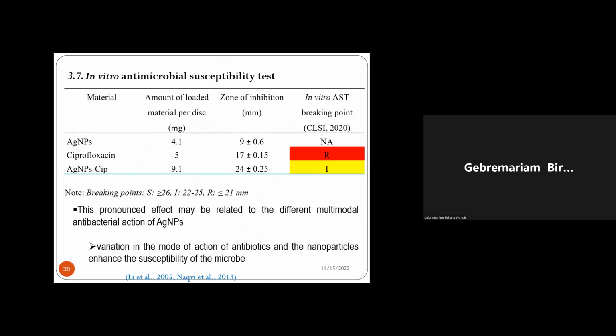And finally, we determined the antibacterial efficacy, comparing pure ciprofloxacin, pure silver nanoparticles, because both of them have an antibacterial effect, and silver nanoparticles loaded with ciprofloxacin. So as you see from the result, loading of ciprofloxacin on silver nanoparticles, or conjugation of ciprofloxacin with the nanocarriers, enhances the efficacy of ciprofloxacin from resistance to intermediate effects. As you see, the breaking points are: if it is greater than 26 millimeters, the drug is active, or the microbe is highly susceptible to the antibiotic. If it is between 22 to 25, it is intermediate efficacy. And if it's less than 21 millimeters, the microbe will still be resistant.